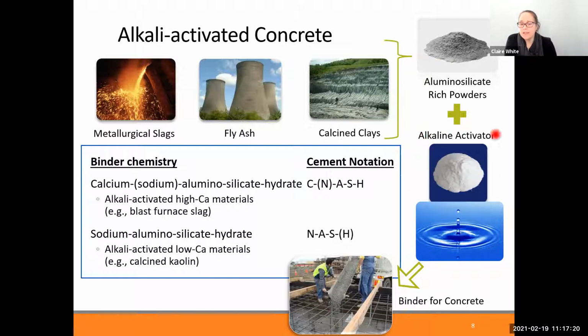And so you're getting a similar binder that's holding sand and rocks together to make a material that looks and acts like concrete at a macroscopic level. But the fundamental binder that gives the concrete strength has differences to Portland cement concrete. So you can get ones that are very rich in calcium, and here it's called a sodium substituted calcium aluminosilicate hydrate gel. We're going to talk about this quite a bit today.